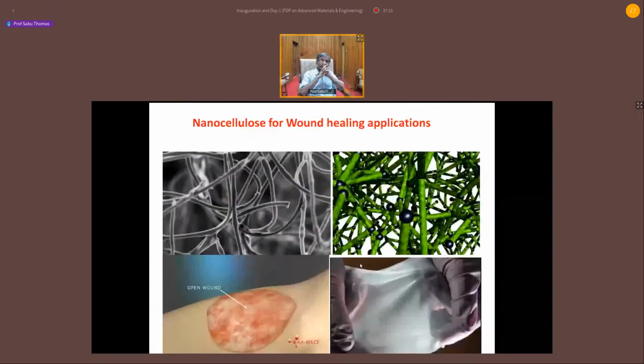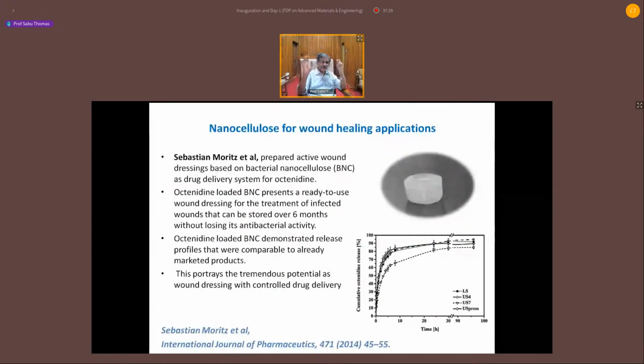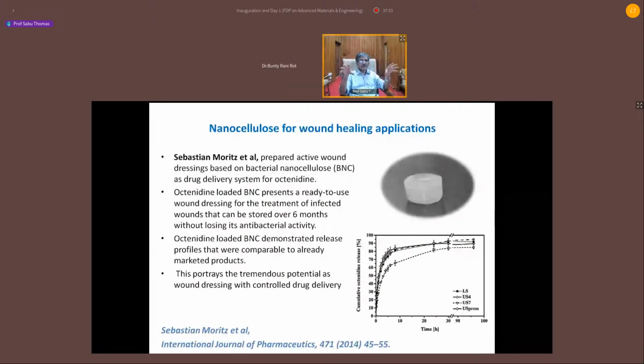Nanocellulose is an excellent material for wound healing. The excellent platform for sustained release of antibiotic. I wanted to show you the nice work of Sebastian Moritz. They introduced antibiotic into aerogel of nanocellulose. They made aerogel. They made use of bacterial nanocellulose and aerogel. And from this aerogel, you can see the release profile. The antibiotic is released in a sustained fashion. You see? And they have concluded that it's a fantastic wound dressing material with a controlled drug delivery process.